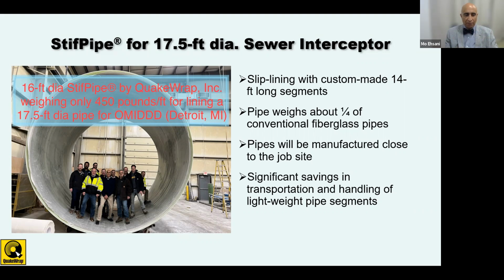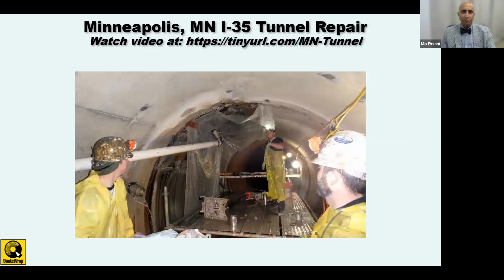Right now, the fiberglass pipe manufacturers in the US can make a pipe of about 10 or 10.5 foot in diameter at most. So notwithstanding the fact that they can't make a pipe this big, even if they could, let's say the pipe was being made in Texas and this job is in Detroit, you couldn't transport it economically over those long distances. We are in fact making these pipes in 14-foot long segments, because two segments of a pipe can be put on a lowboy truck, and then that can go under the overpass bridges and be driven and delivered to the job site.